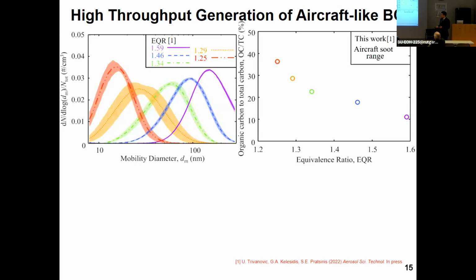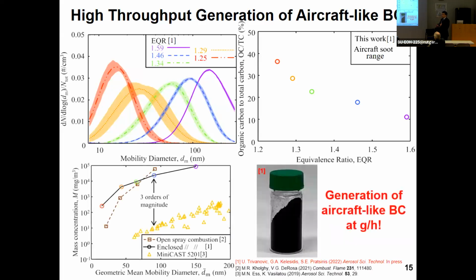Now, what is the benefit over here? The benefit is that we can actually produce very large mass concentrations. Of course, there are already commercial reactors that try to do this, but unfortunately, their mass concentrations are very low. While with the new reactor that we have over here, we can produce 3 orders of magnitude more particles in our laboratory. To better understand, I'm just showing you over here a picture of a vial with black carbon nanoparticles that are similar to aircraft engine emissions, and we just obtained this in just 10-15 minutes.